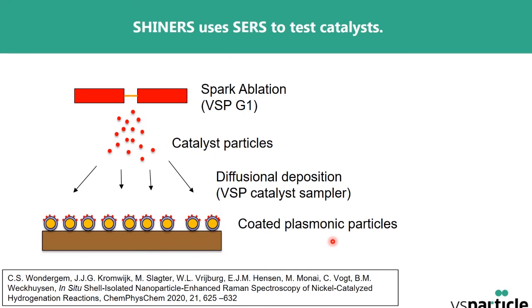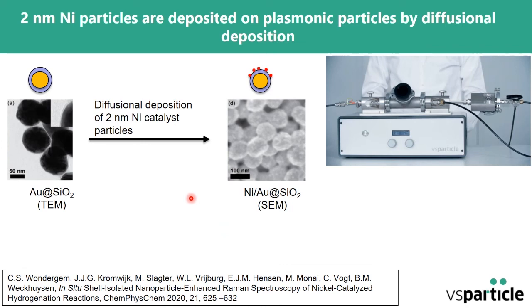In the end, I would like to mention another method that is called SHINERS, and very recently the group of Bert Weckhuysen has shown that surface enhanced Raman can be used to follow a catalytic reaction. For that, you need these plasmonic particles on the surface, and these plasmonic particles then have to be covered by the catalyst that you want to test. It's also a screening method. And of course, you can produce these very simply with the spark generation process. And this was done by this group.